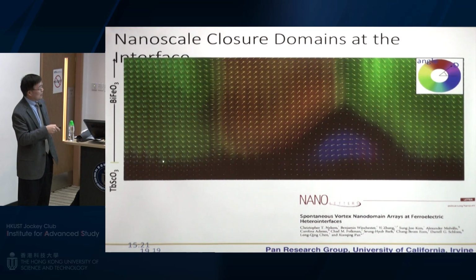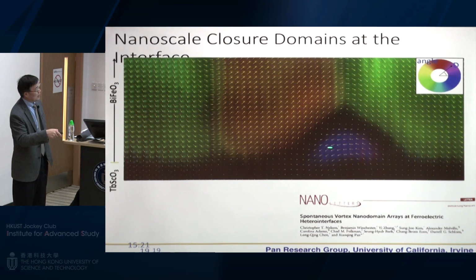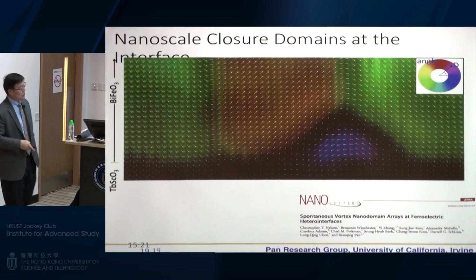The polarization heads terminate at the interface, giving positive charge, and the tails terminate here, giving negative charge. From positive to negative, the internal field points in that direction. From here, positive to negative points in the opposite direction. Therefore, in this area, the internal field created by the bound charge favors the polarization change in this direction, but does not favor this polarization configuration. That's why the polarization has to rotate and form this kind of vortex structure.